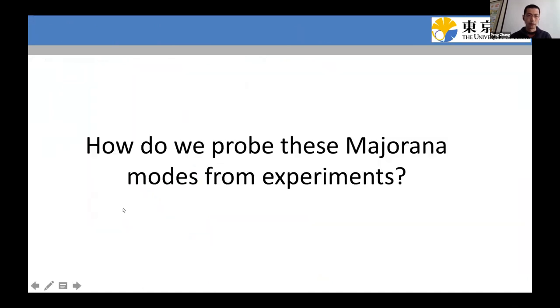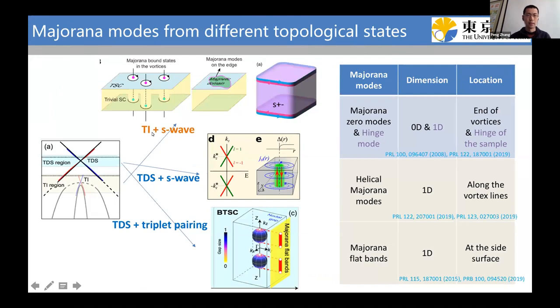From these different topological superconducting states, we can expect different Majorana modes. For this topological insulator plus S-wave superconductivity case, first we expect Majorana bound states in the vortices. Also, if we can deposit a magnetic domain on top of this material, then we can expect Majorana chiral modes along the domain edge. People also propose that there are Majorana hinge modes in this material.